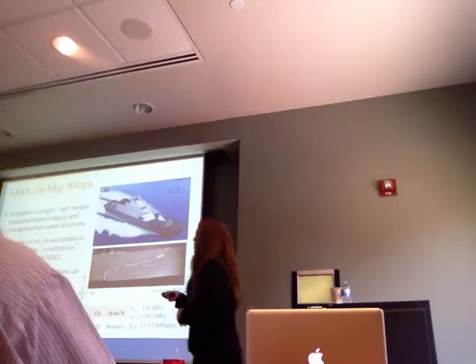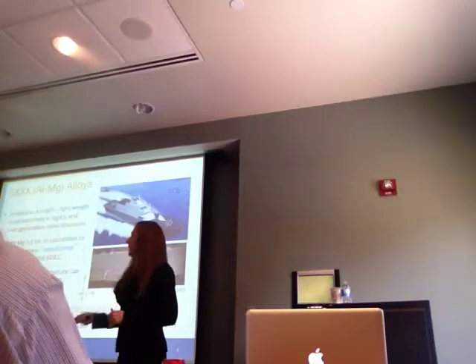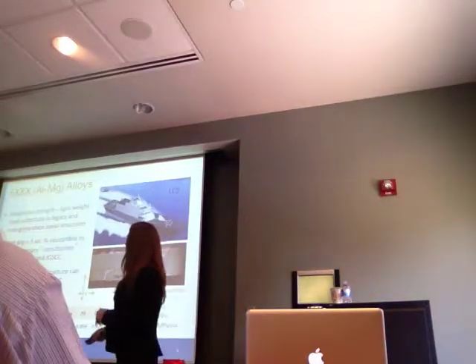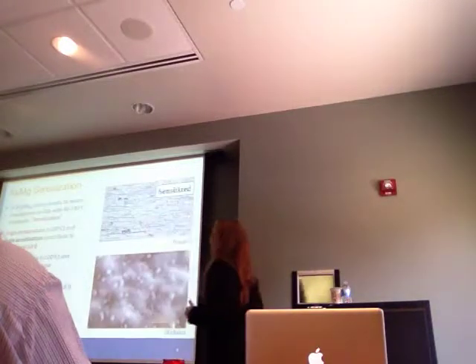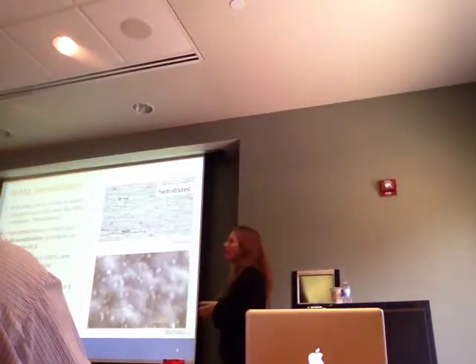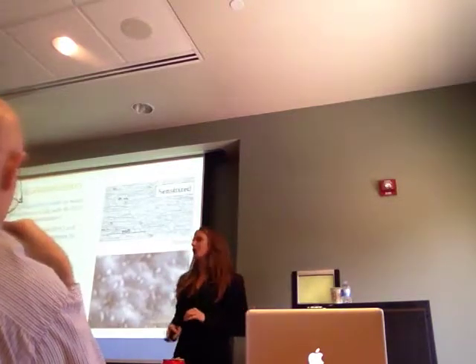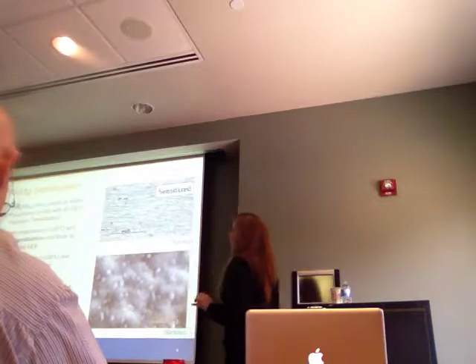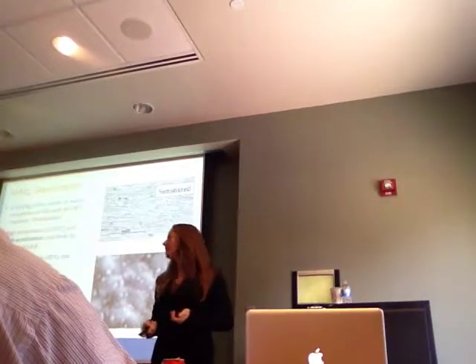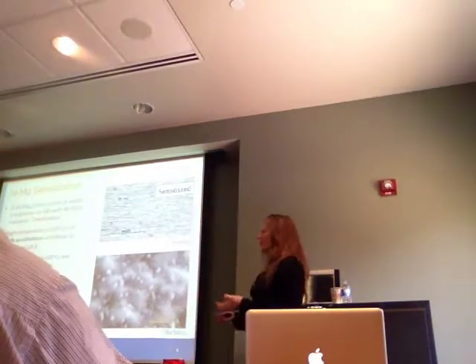The other thing that's important to note is that the way the plate is rolled and forged, you have a grain structure that leads to mixed mode cracking. So you might have a crack that starts in this direction and then changes to this direction along the grains. So what is sensitization? Well, sensitization occurs when your magnesium diffuses to the grain boundaries and causes the precipitation of a beta phase, which is an Al3Mg2 particle. This particle is mainly on the grain boundaries, and it can form at 40 to 230 degrees C. So all the surface temperatures in service could cause this sensitization.